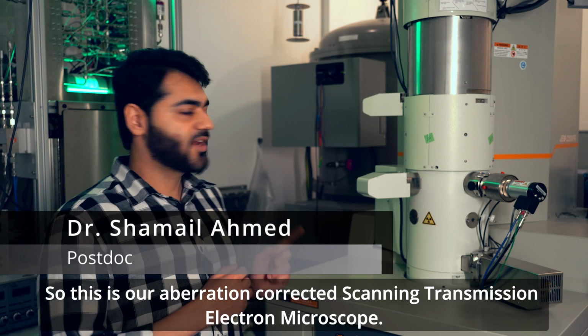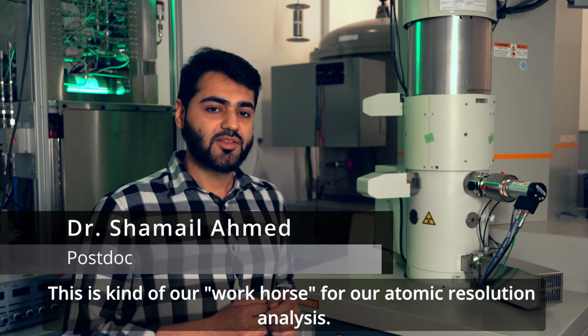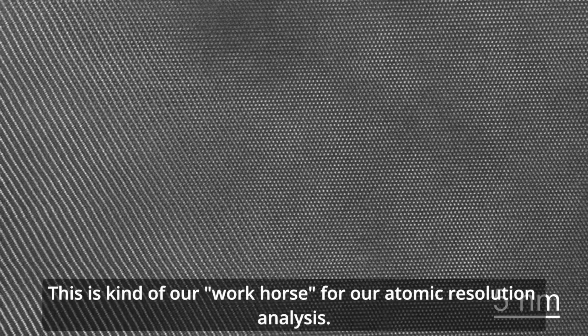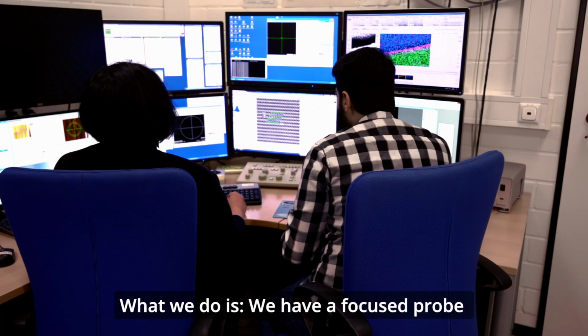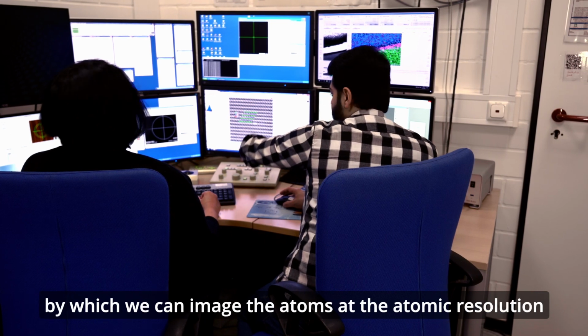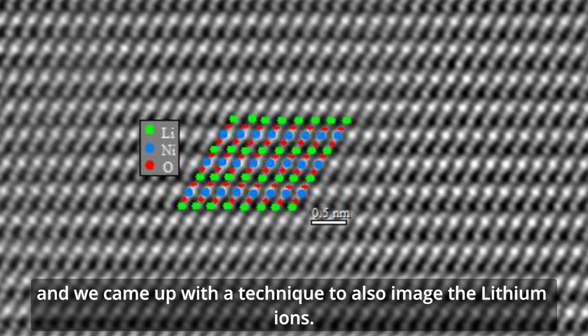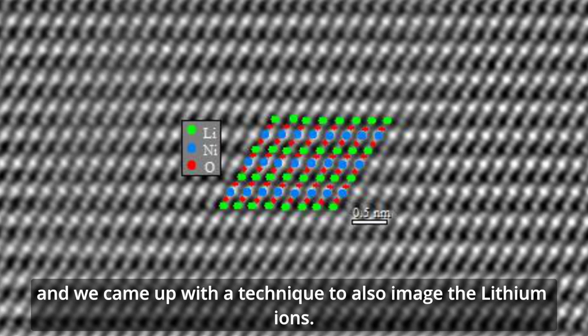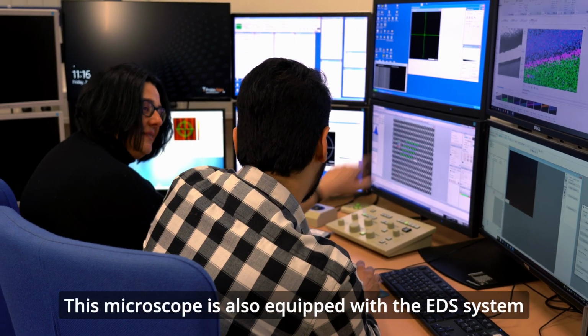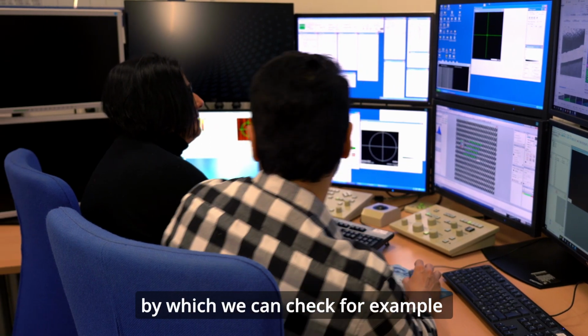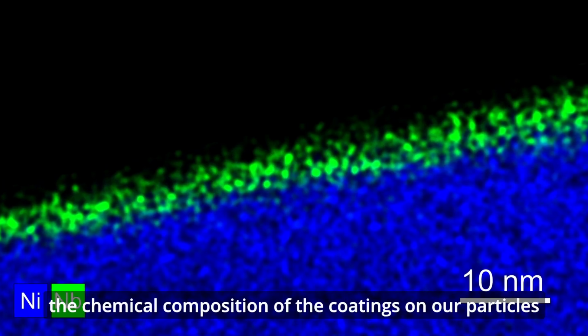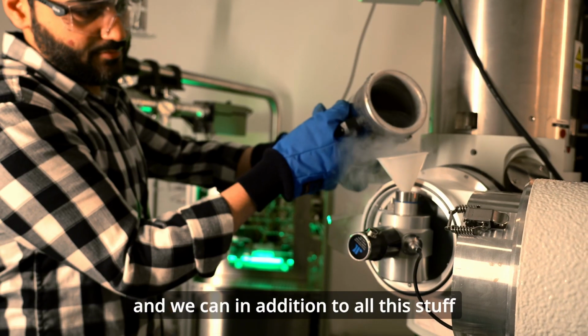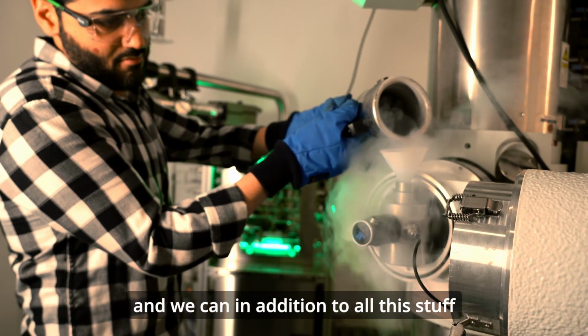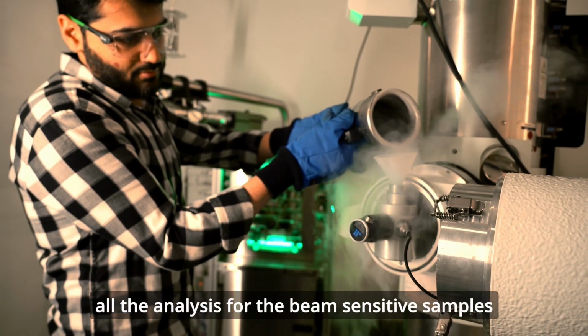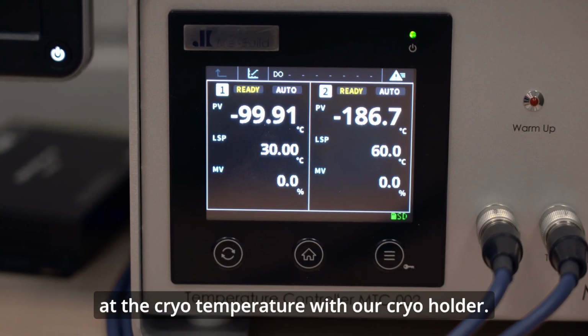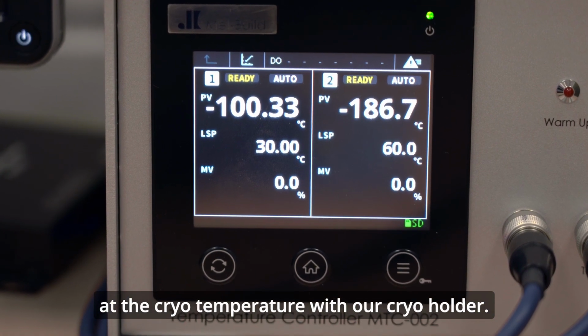So this is our aberration-corrected scanning transmission electron microscope. This is kind of our workhorse for our atomic resolution analysis. What we do is we have a focused probe by which we can image the atoms at atomic resolution, and we came up with a technique to also image the lithium ions. This microscope is also equipped with the EDS system by which we can check, for example, the chemical composition of the coatings on our particles. And in addition to all this, we can do all the analysis for the beam sensitive samples at cryo temperature with our cryo holder.